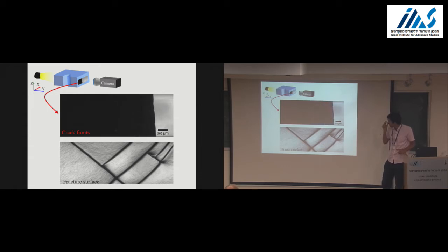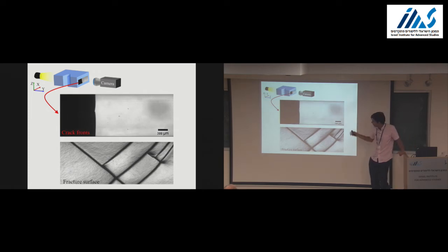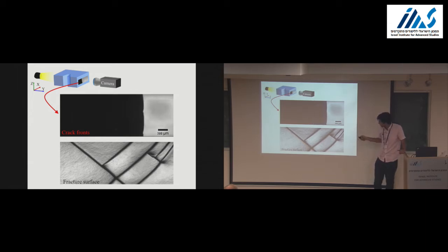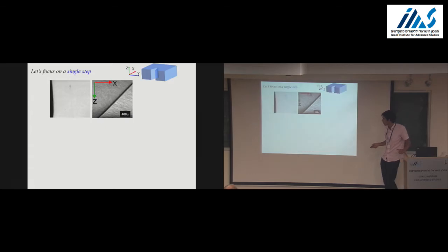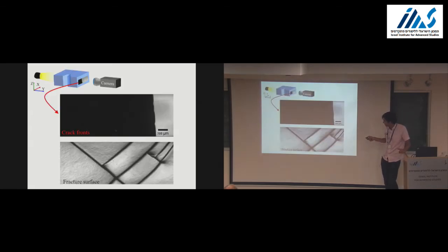facets. You can see that there are very delicate, slight perturbations to the crack front as it propagates, and each of these small perturbations corresponds to one of these steps. What's the time scale? Sorry. I can tell you the velocity of the crack, which here is about 4 centimeters per second. So I'm thinking the whole thing must be something like a few microseconds, milliseconds.